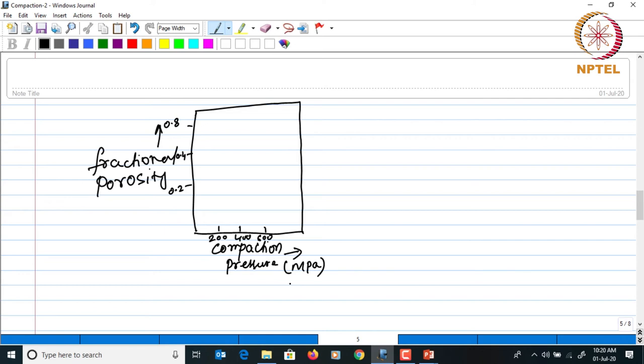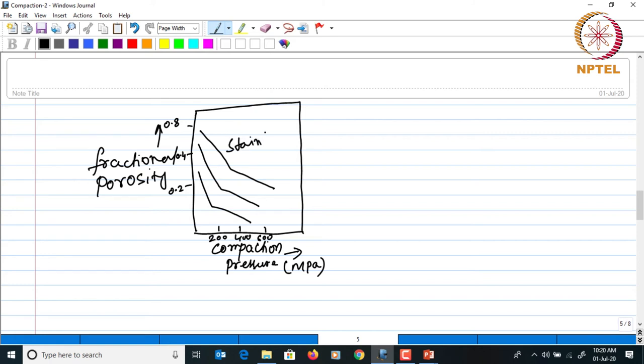The pressure is in megapascals. As the pressure increases, the fractional porosity decreases. This behavior is different for different materials — for example, the top curve is for stainless steel and the lowest is for copper. At around 300 MPa there is a change in slope, indicating a change in the compaction mechanism or compaction behavior when the pressure exceeds a particular value.